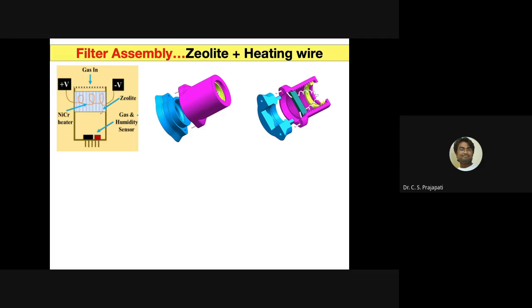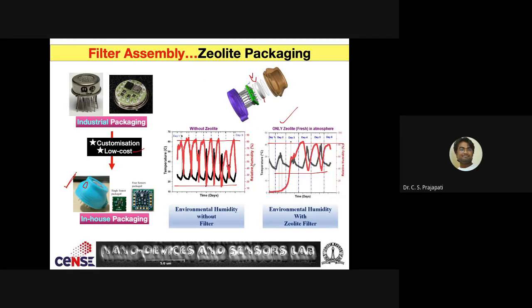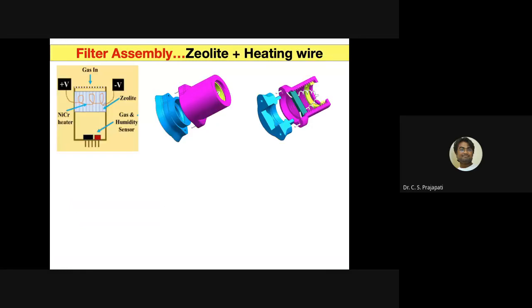So we did the filter assembly. What we did is, to minimize this change further, we inserted one wire, the nickel chromium wire, and we heat it at a certain temperature. So what happens is that any amount of moisture going in is reflected back from here, and only a certain amount of moisture reaches the sensor part. And we plugged in a humidity and temperature sensor over here just to understand how much moisture is going inside.